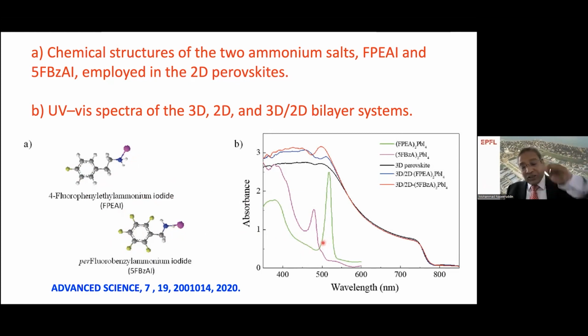Now, if we deposit these two-dimensional perovskites on top of the three-dimensional perovskite, how do the spectral responses look? The reference sample is the black one; there is no two-dimensional perovskite on top. Now we used a two-dimensional perovskite containing fluorophenylethylamine with one fluorine. That's the blue curve. And if we use the pentafluoro, that's the red curve. In the UV part, below 500 nanometers, you can see distinct differences, but the onset is mostly dominated by the three-dimensional perovskite.